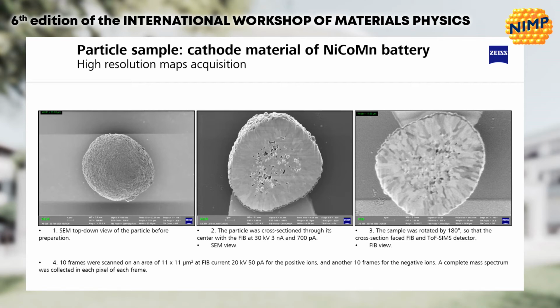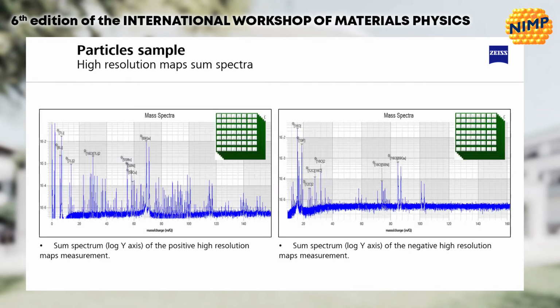Once we did that, the next step is to correlate this contrast image that we get, in this case a secondary electron image from the electron microscope. We would like to identify the different isotopes from the lithium battery inside this cross section. And this is what we did. We performed from every single point of the SEM a mass spectrum from the surface. And what we see here on the left is a mass spectrum of positive ions for one single point in the sample.